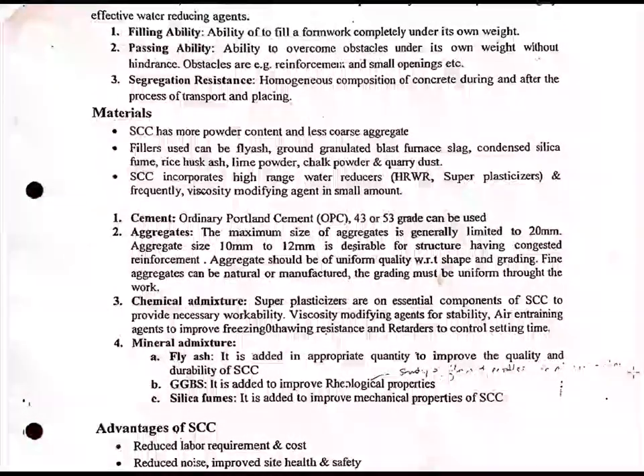And there is one more agent called viscosity modifying agent that is used for stability, which will prevent the aggregates and cement paste from getting separated. There is segregation resistance for stability of the concrete. Air entraining agents are also used if in that area freezing and thawing is the case. And then retarders are used. Why are retarders used? Since it is flowing, the cement has some setting time. If the concrete starts setting, then that flowability or workability will get reduced because it will be getting hardened. To delay the setting time, retarders are used.